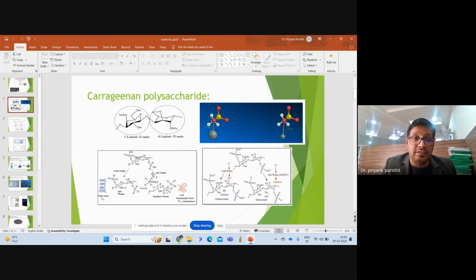Then our group replaced this potassium ion with calcium ion. We checked that calcium ion has a different capacity. We tried to maintain the distance between calcium and potassium. We saw that calcium has a smaller size, and the bond distance is 2.4 angstrom, which shows that it has more bond strength. Then in normal water, it was sure that it was not dissociated.